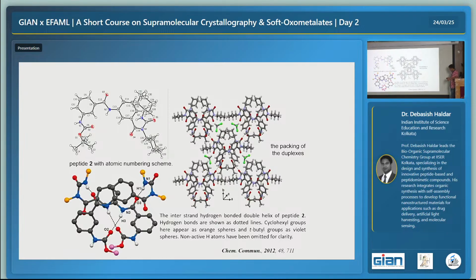But for the longer version, with 2 meta-aminobenzoic acid residues in the sequence, it forms a duplex, double helical structure. The double helix is stabilized by intermolecular hydrogen bonding between the 2 strands as well as pi-pi stacking interaction from the aromatic moiety. And this is the packing structure of the compound in chloroform.